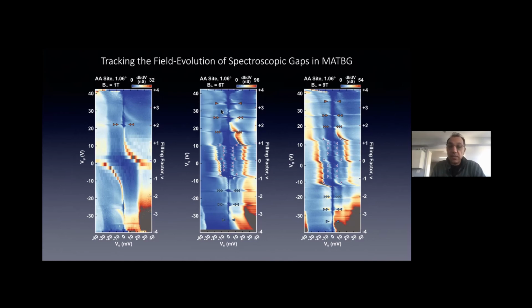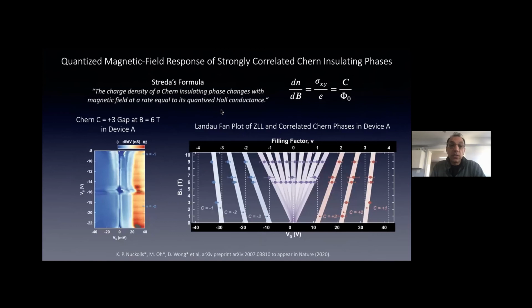I know this is a busy slide, but what you can do is take the center of those gaps and plot them as a function of magnetic field and as a function of gate voltage. If you do that, you basically find that it does indeed follow the Streda formula. You resolve the features associated with the zeroth Landau level, which is what's in the middle here of the plot near the charge neutrality point.